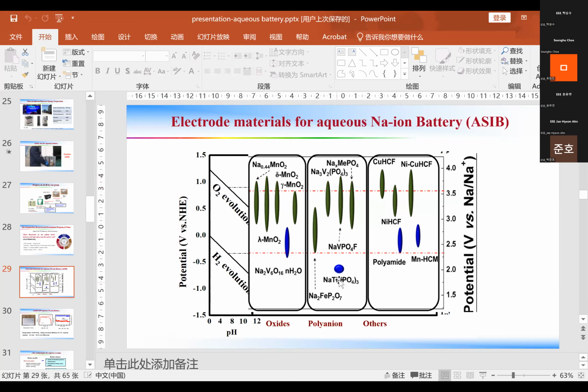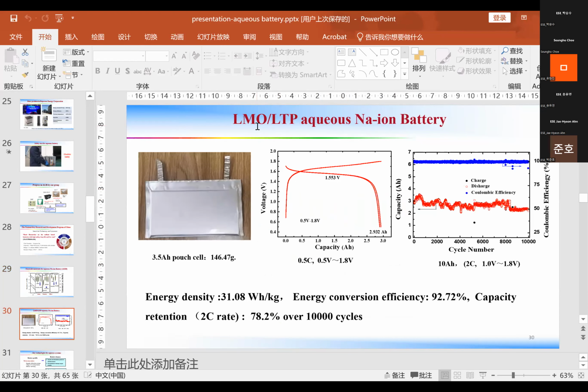So we chose that, but for the anode negative material we can use lithium titanium phosphate, and we add lithium because we cannot find a suitable sodium-based positive electrode material, and we use the spinel. This is a hybrid sodium-ion battery. Normally we can get a specific energy density of about 30 watt-hours per kilogram, and it can run over 10,000 cycles with a capacity retention of over 78%. And this work took 5 years to develop.